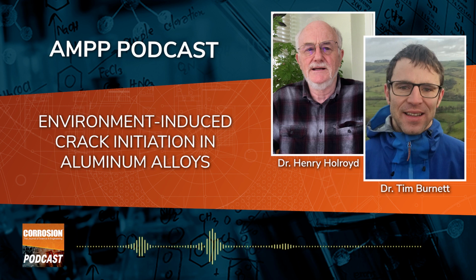Yes. And you talk about initiation. What counts as the initiation stage or early stages of crack growth? If I address this from two aspects, from a practical consideration, one could argue that the early stages of cracking is where it is only cosmetic. In other words, it's not going to limit the performance of a structure or a product in real life. And I would argue that is something that we've learned to live with. Now, one can look at it from a science-based response, saying the early stages of cracking is when you get to a stage where that cracking will continue and would be a service issue. As you can see, I come more from the application of things as opposed to the raw science of it, which is why I work with Tim, of course. So I hope that gives you a feeling, because you can have cracking which is not going to be a problem in real life.